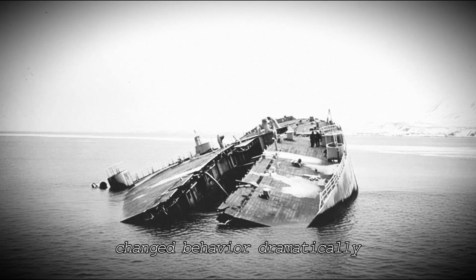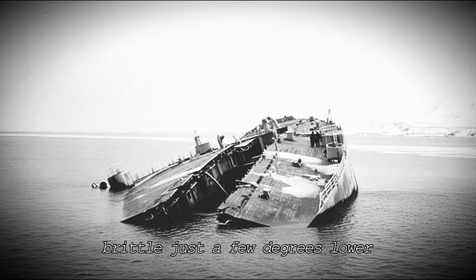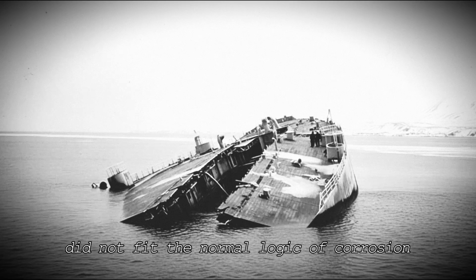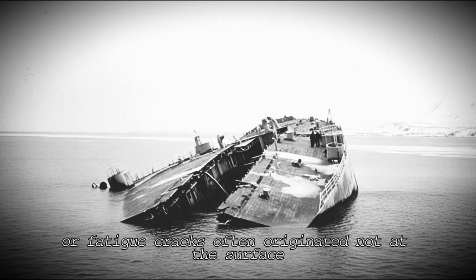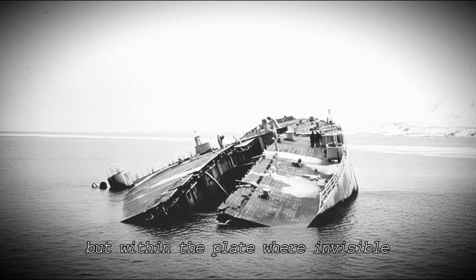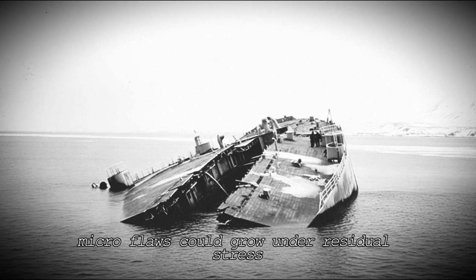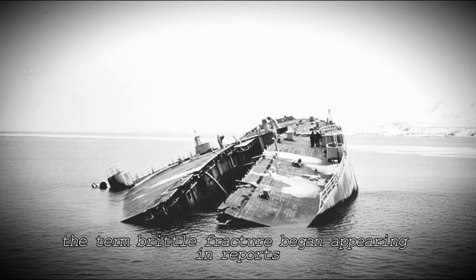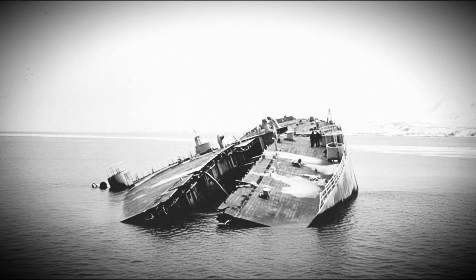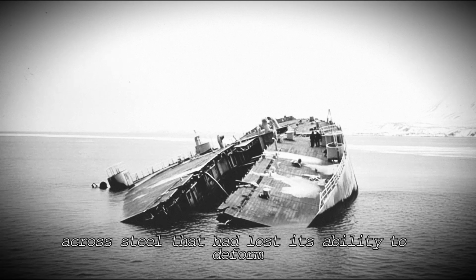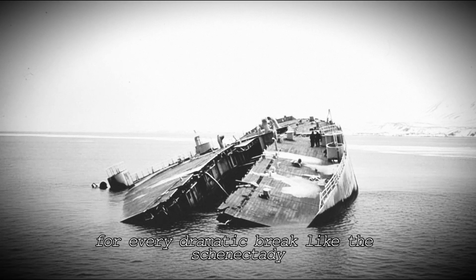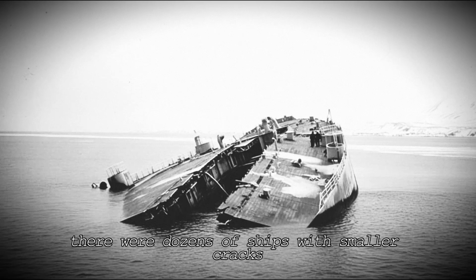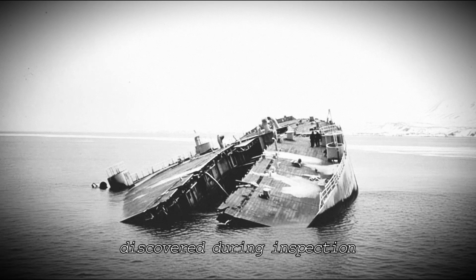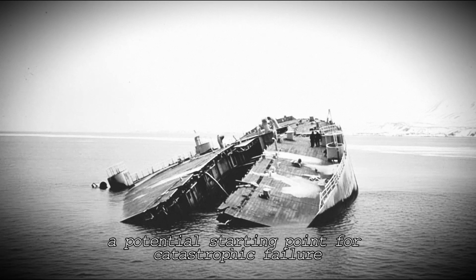Some steels, they noted, changed behavior dramatically with temperature. Ductile at one point, brittle just a few degrees lower. The phenomenon did not fit the normal logic of corrosion or fatigue. Cracks often originated not at the surface, but within the plate, where invisible microflaws could grow under residual stress. The term brittle fracture began appearing in reports. It described a failure that propagated almost at the speed of sound across steel that had lost its ability to deform. For every dramatic break like the Schenectady, there were dozens of ships with smaller cracks discovered during inspection, each one a potential starting point for catastrophic failure.